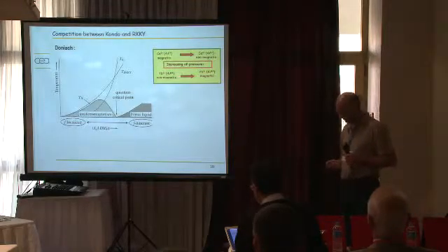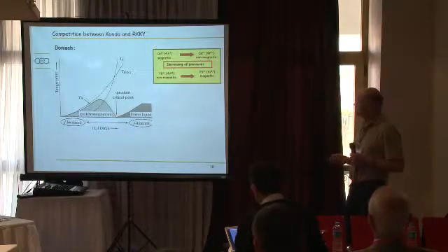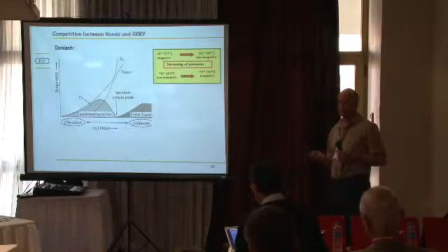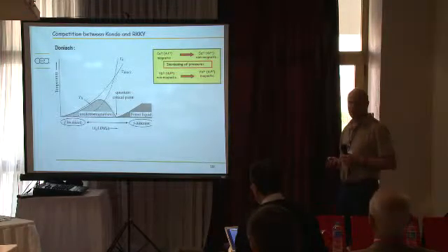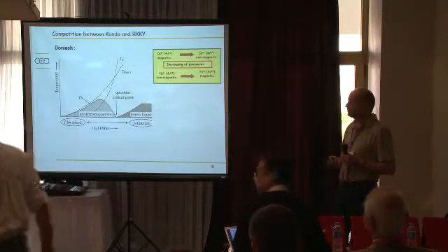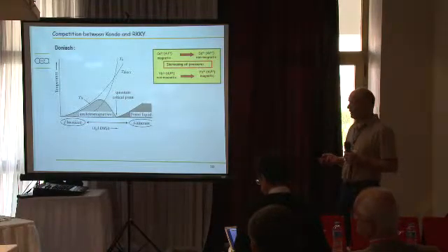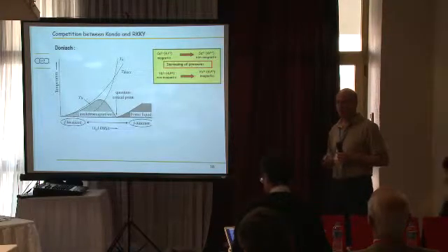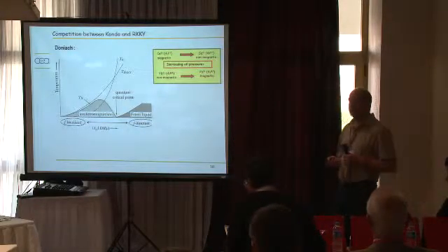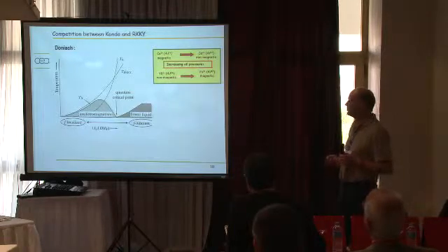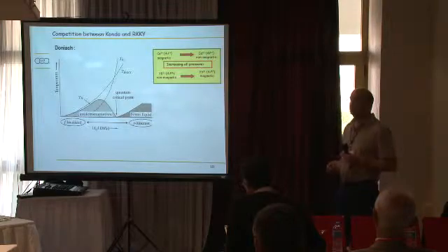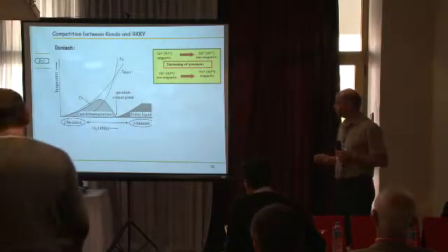Now, if we want to look in detail at what's happening to magnetic instability, the usual approach is the Doniach diagram. Doniach pointed out that the ground state of the system is going to depend on the competition between two different effects. One is the Kondo effect, which, by screening of the local moments by the conduction electrons, is going to reduce magnetism. The other is the well-known RKKY interaction, which is going to tend to promote a magnetic ground state. Both these effects depend on the same parameter, which is basically the interaction between the 4f electrons and the conduction electrons, but they don't depend quite in the same way.